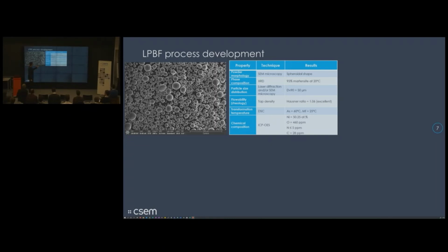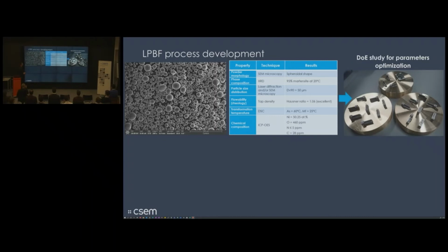Transformation temperature, in this case, we had austenite start temperature 60 degrees and martensite finish 25 degrees, which is the right transformation temperature to demonstrate shape memory effect at room temperature as the reference. And the chemical composition was also important, to have a low amount of impurities and the right amount of nickel so that it has the transformation temperature as shown.